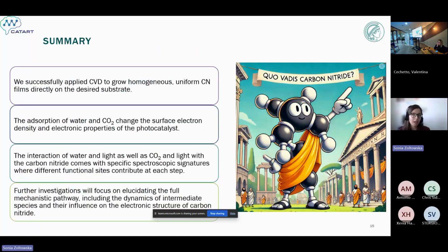So to sum up my presentation today, I can clearly say that we can successfully apply CVD to grow homogeneous and uniform carbon nitride films directly on the desired substrate. We also discovered that the adsorption of water and CO2 changes the surface electron density and electronic properties of the photocatalyst. We can track the interaction of water and light, as well as CO2 and light, with the carbon nitride. That comes with a very specific spectroscopic signature, and each functional site contributes to each step.